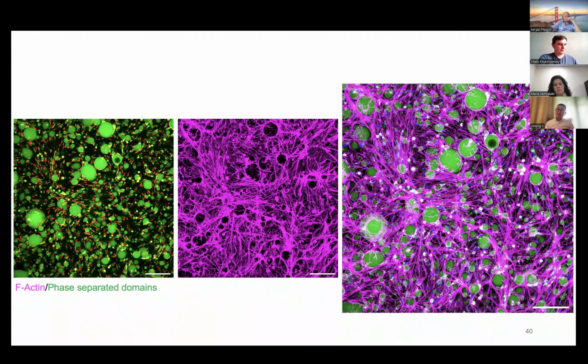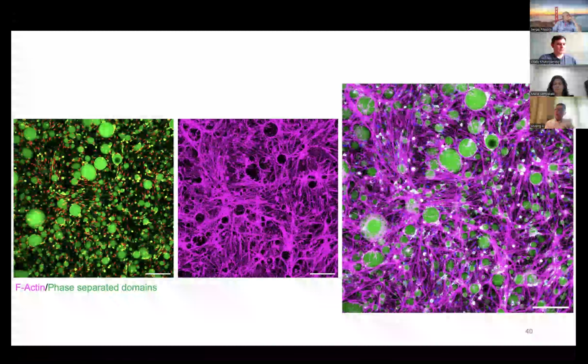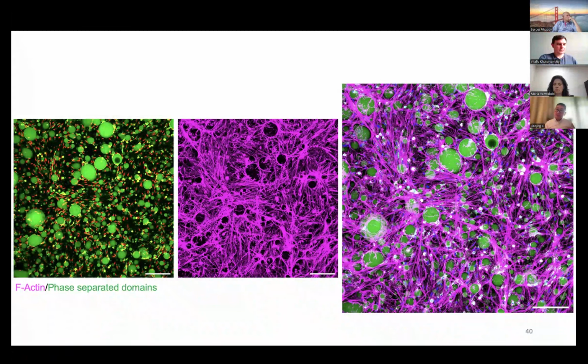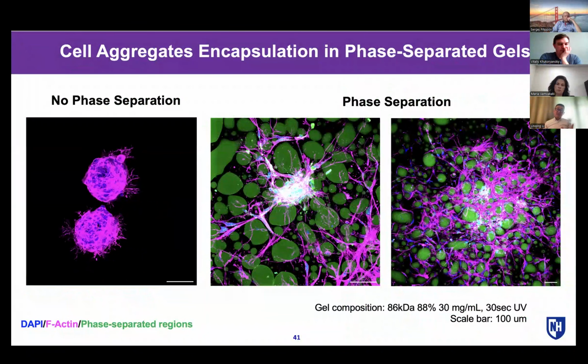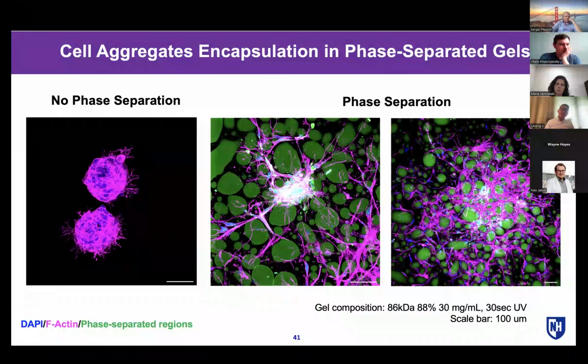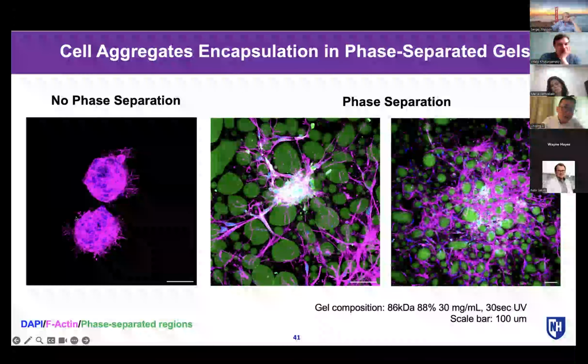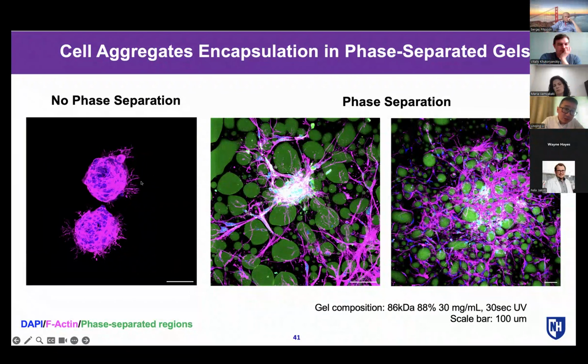But now if you have this heterogeneity in the mechanical properties, and then use these domains as a sort of 2.5D, because it's not truly 2D, it's not truly 3D, so you have some sort of interface. So now you can use this interface to guide the cells through to migrate and take over the entire matrix. So not only do we have this observation of single cells, we're able to show that in the aggregates as well. Here, as you can see, in the non-phase separated gels, the aggregates only show some sort of protrusions to try to engage with the matrix.